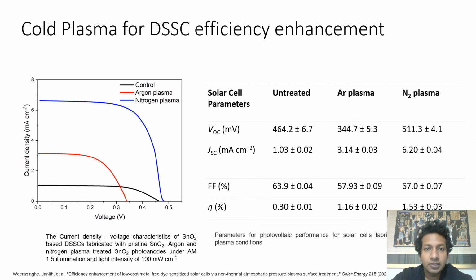Additionally, plasma-treated tin oxide is capable of acting as a photocatalyst for the formation of reactive iodine species to facilitate the redox reaction of the electrolyte. A combination of all these favorable effects for the nitrogen plasma-treated photoanode significantly increases the overall photoconversion efficiencies of the fabricated DSSCs in a single-step treatment.